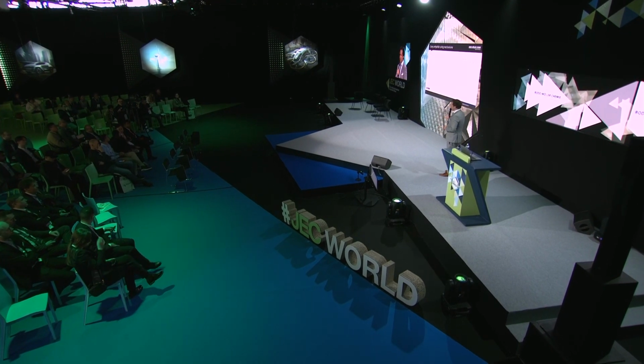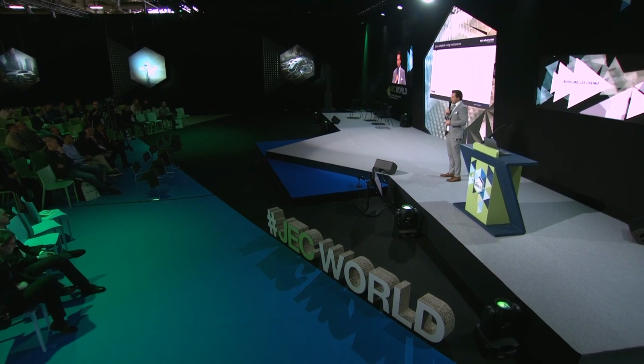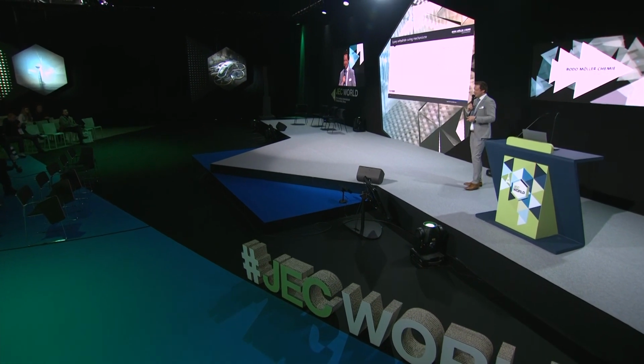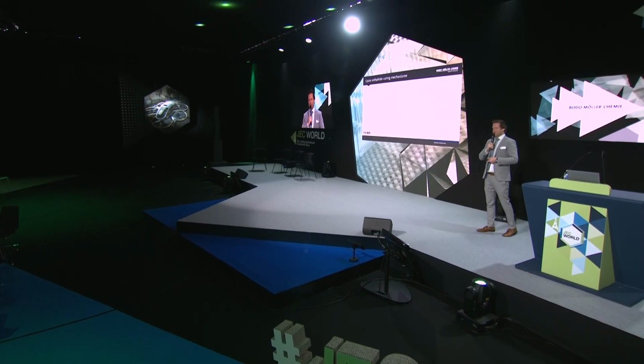Basically here we have a two-step reaction. In the first step, the anhydride reacts with a hydroxy group in the epoxy resin, and then in another step, the anhydride reacts with our epoxy group. This step is critical and important for the curing and the network formation of our epoxy network. What is quite important here is that with anhydrides, out of a difunctional epoxy resin, you create a tetrafunctional reactant because you have this two-step reaction.